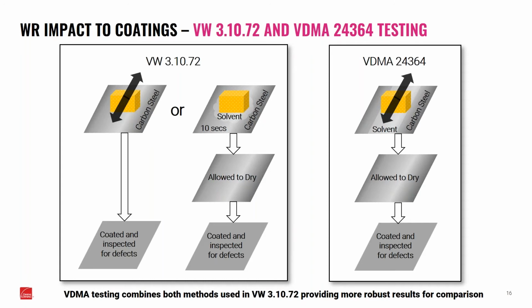And what they're looking for is those little pinholes that we just talked about. Or they'll take a piece of carbon steel, put insulation on top of it, and pour solvent through the insulation, and then allow the insulation to sit in that solvent for 10 seconds before they remove it. They'll allow it to dry, and then they'll coat it, and again, they'll look for those defects. So depending on which method you use could have an impact on whether your waterproofing agent is going to impact the ability to coat something.